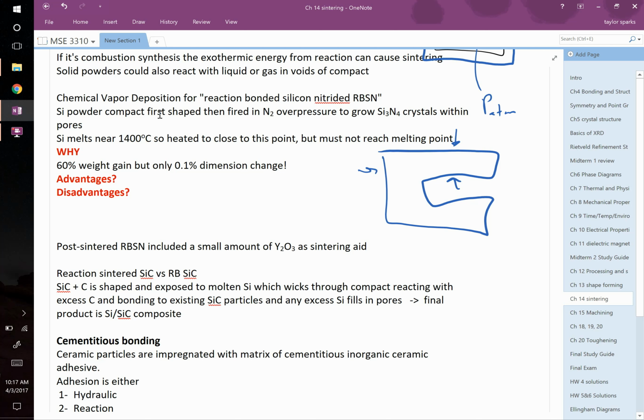Yeah, what if there's some oxygen left over? Then you're going to form silica. That might be not what you're looking for. Let's assume we even get it all out, though. The problem that they run into with this is that you've got a bunch of little particles in your ceramic, right? And you're starting to introduce nitrogen gas, and you're hoping that it's going to then form a new particle of silicon nitride.